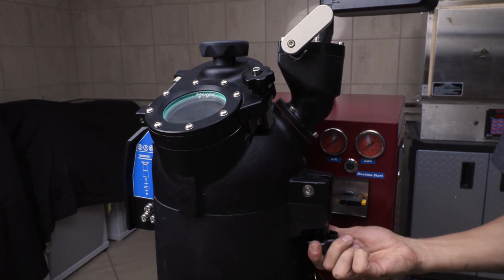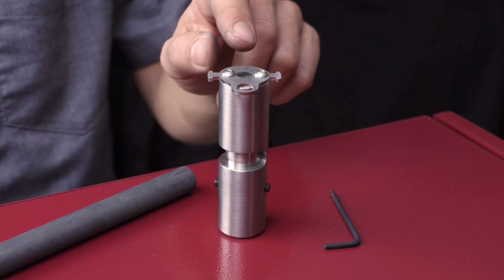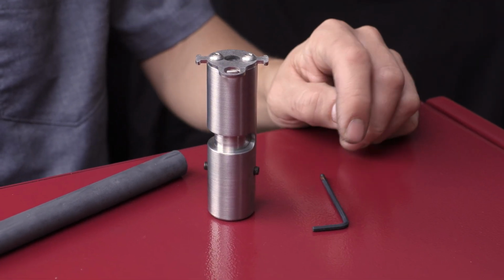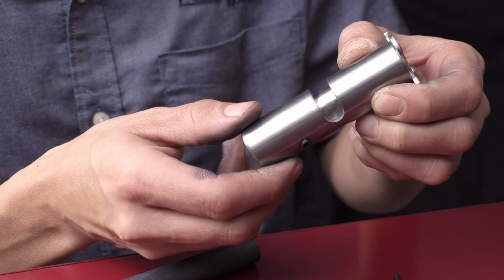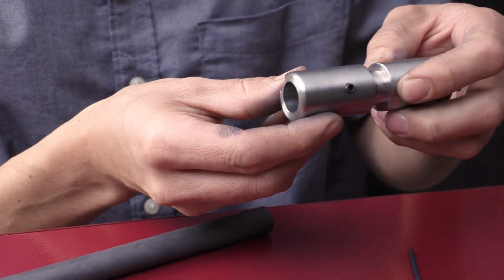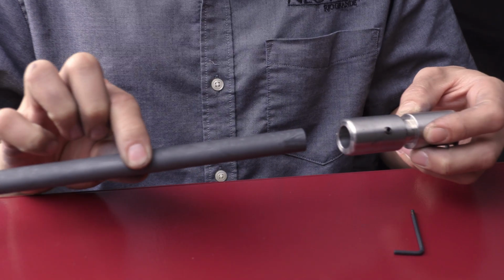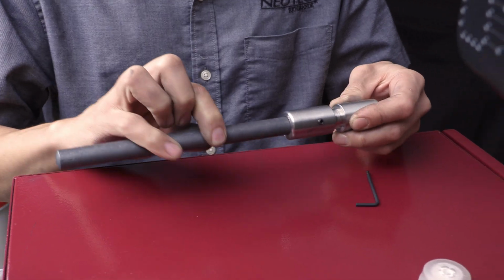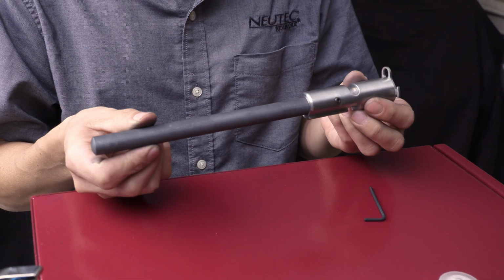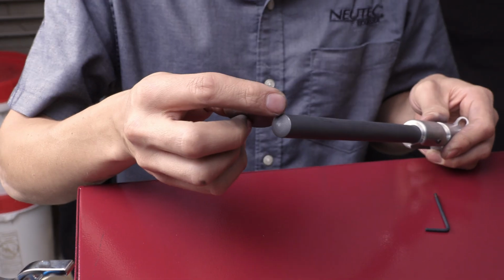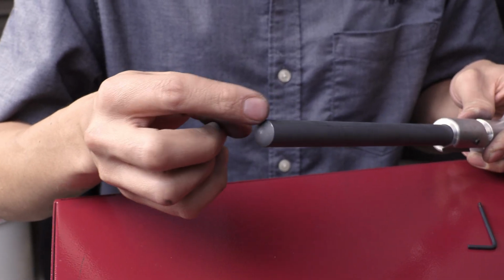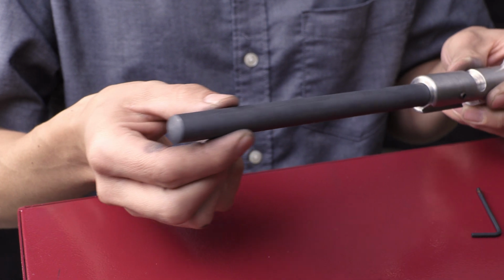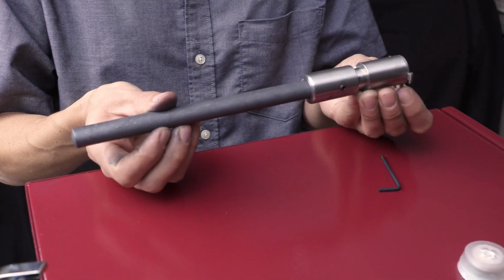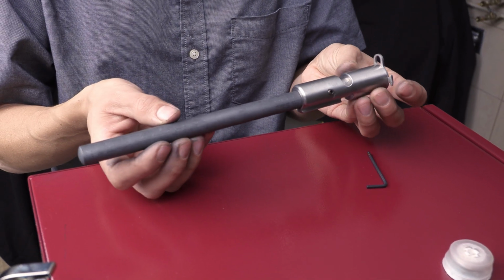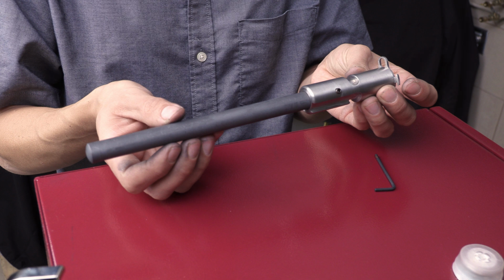Now we will need our sealing rod holder and the included 2.5mm Allen wrench. The seal rod holder holds the seal rod and is able to be removed together with the seal rod when changing over the consumables to avoid metal cross-contamination. The sealing rod is what keeps the metal inside the crucible until it's at the right temperature. The sealing rod should be inspected before each casting day to ensure that there is no damage or wear that could cause issues with the castings. A worn sealing rod could lead to metal leaking by the seal rod and cause no-fills.